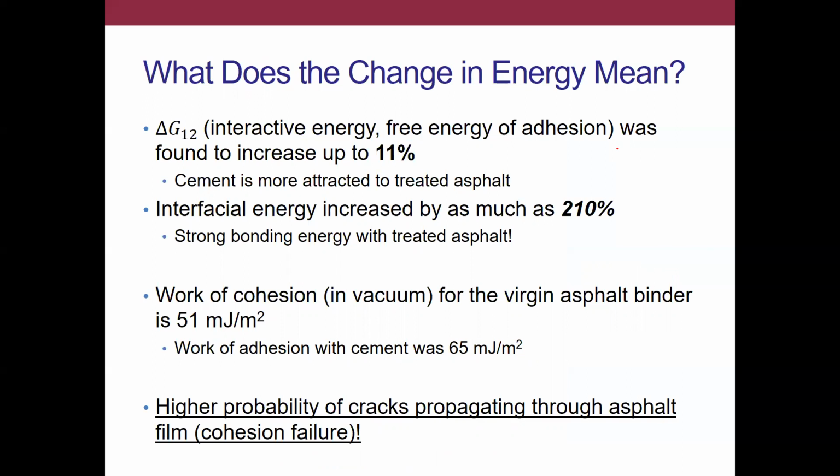In other words, the cement has a greater chemical affinity for the oxidized asphalt. So that is a significant increase. I'm sorry, the interactive energy increased by 11%. The interfacial energy increased by as much as 210%, right? So again, this does suggest very strong energy.